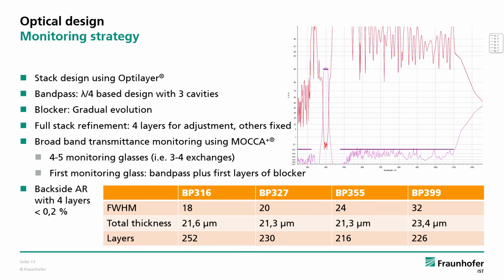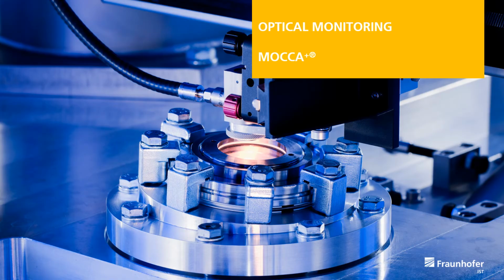The deposition was controlled using the modular optical coating control application MOCCA+ that was built in our institute. We decided to use 4 to 5 monitoring substrates depending on the layer number. Within this, the first monitoring substrate is used for the quarter-wave thickness bandpass and the first layers of the blocker. On the next slides, I want to show some details of our in-house developed MOCA system. You see light that comes from the deposition machine to a reflective collimator that puts the light into the fiber.